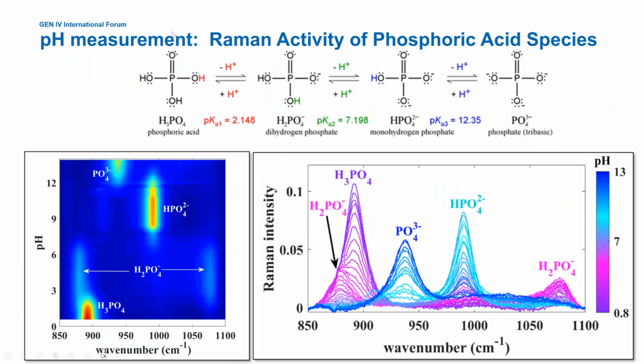The next application I want to talk about is pH measurement using the Raman technique. What I have shown here is a series of phosphoric acid speciation as a function of pH. On the left-hand side, this is phosphoric acid, the triprotic form. As you increase the pH, you can remove a proton by titration, and it goes to the diprotic form. Remove another hydrogen by going to higher pH, you go to the monoprotic form, and then go to the fully deprotonated form of phosphate in this case.